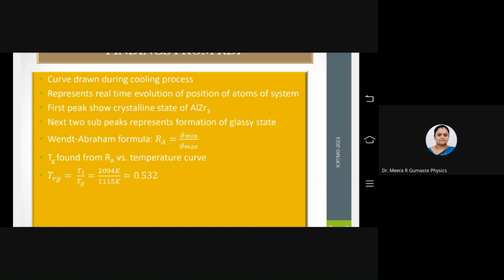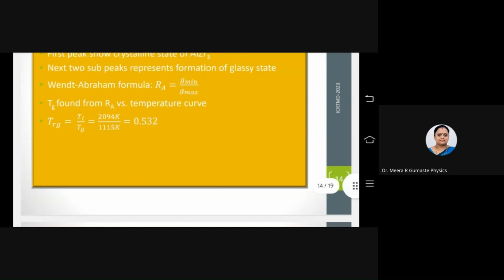And the TRG, that is the reduced glass transition temperature, you see here TRG is equal to TL by TG. So TRG is reduced glass transition temperature. So that value came out to be 0.532 in this case. So any value of TRG around 0.5 marks the formation of bulk metallic glasses. That means these materials are good bulk metallic glasses. Their glass forming ability is good. So this confirms the formation of bulk metallic glasses for the aluminum zirconium alloy. So this number 0.532 confirms that one.